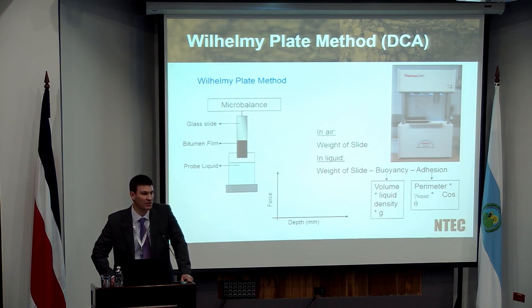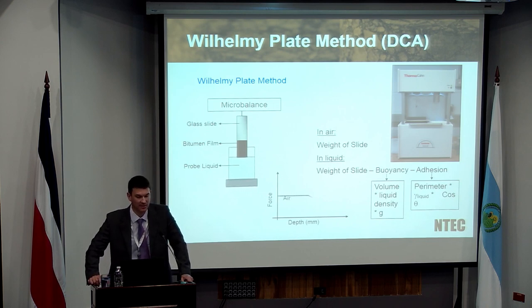Obviously, you've chosen those liquids based on their individual surface energy parameters. And very carefully, using a very highly controlled and accurate microbalance, you slowly drop that glass-covered slide into your probe liquid. What you're going to measure then is the change in effectively weight. It's called a force because we're looking at the force of gravity, but effectively it's looking at how the weight changes as you dip that particular solid bitumen-coated glass slide into your probe liquid.